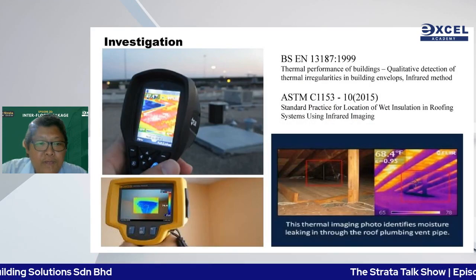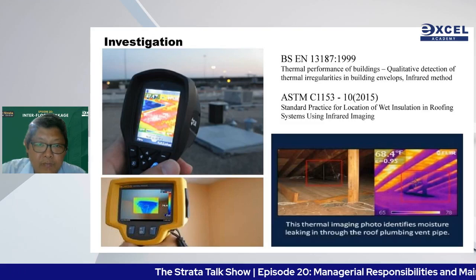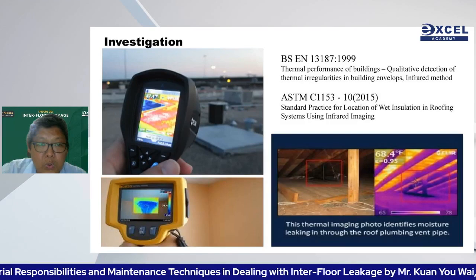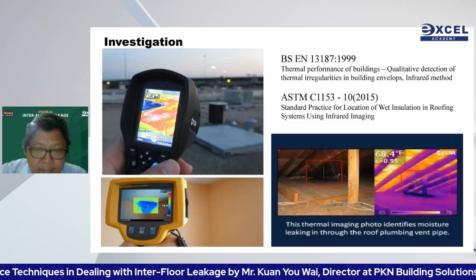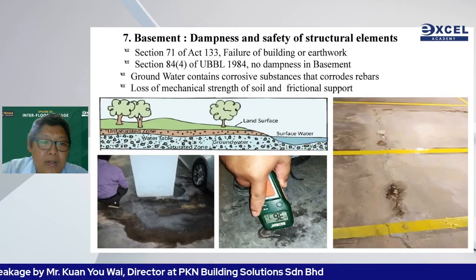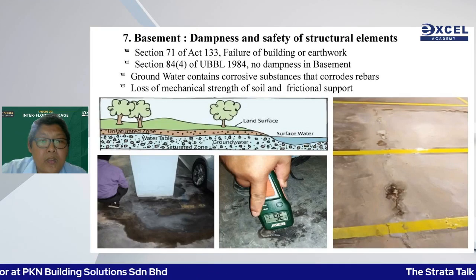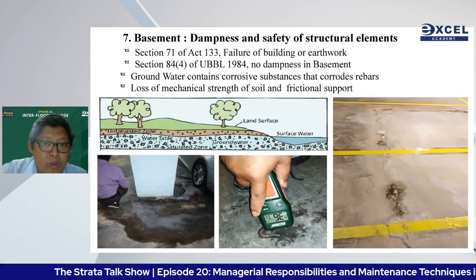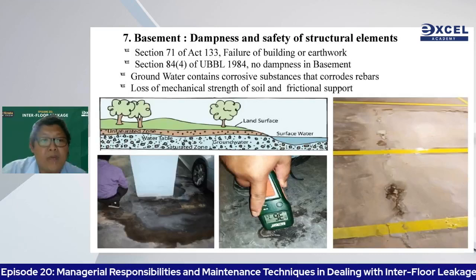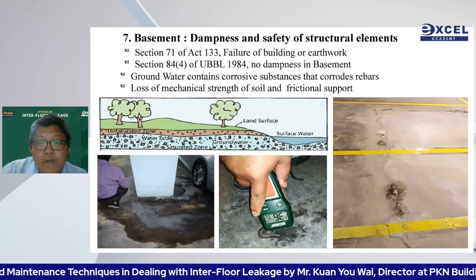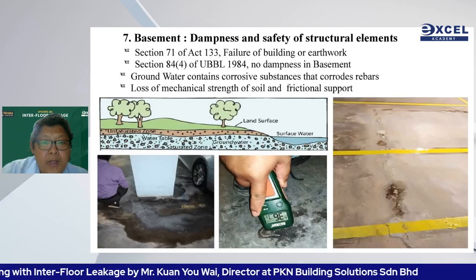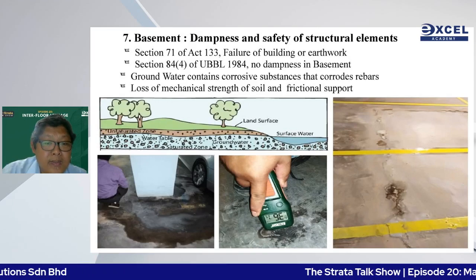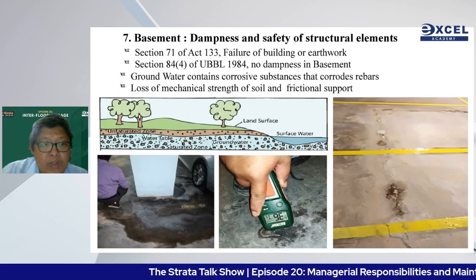For flat roof infrared inspection, ASTM C1153 is the relevant standard for outdoor hot spots and BSEN 13187 for indoor cold spots. Rising water tables are increasingly causing damp basements. Uniform Building By-Law Section 84(4) does not allow any dampness in basements as buildings are not designed to float on water. If water is discovered in a basement or lift pit, further study is required to assess pH and pollutants to understand implications for the foundation.